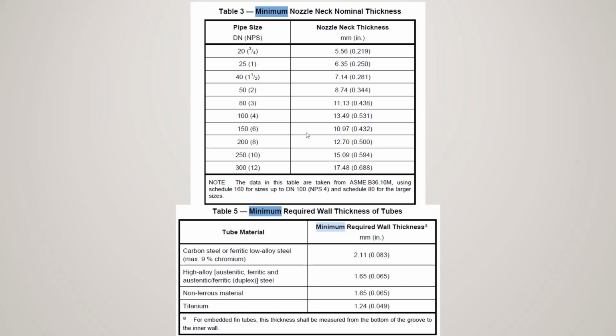Now coming to the tube wall thickness, the carbon steel is 2.11, high alloy and non-ferrous is 1.65, and titanium 1.24. And the most important part here is that for groove embedded fin tubes, the minimum thickness is considered from the bottom of the groove. So automatically, if it is a G embedded fin tube construction, for carbon steel the minimum thickness will be 2.41 and for high alloy steel 1.95, because the groove depth is 0.3 mm maximum, which is 0.25 plus or minus 0.05. So another 0.3 mm has to be added for the minimum thickness.